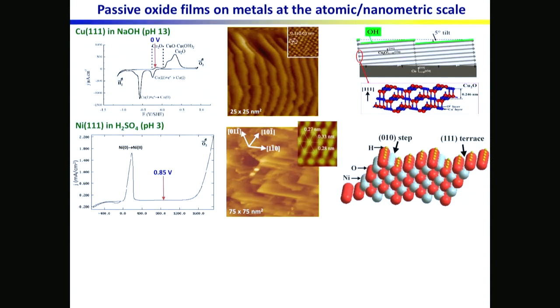The other thing is that you see that there will be sites that are differing at the surface, and it's important at this point to know, for those of you who are not very familiar with the topic, that the enemy for these oxides are chlorides, chloride ions, because they will locally attack the oxide. And there are a lot of chlorides around us, especially in seawater. And from this kind of model, which is directly derived from the STM measurements, we could derive the proper DFT model to calculate and model how chloride ions could replace these OH ions that are formed at the surface.